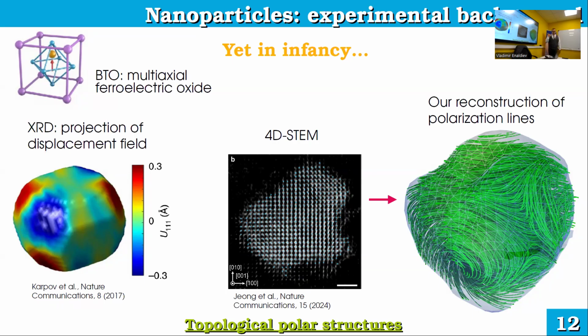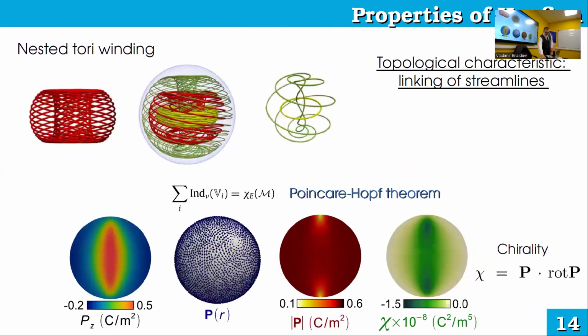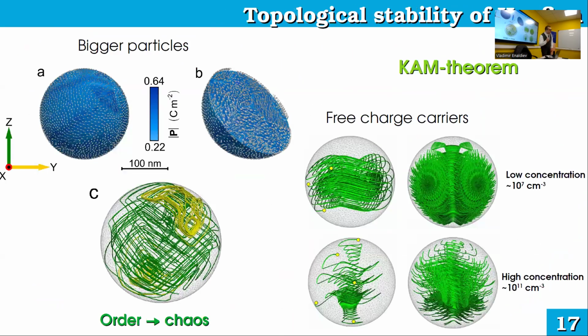Because it's also very important that I showed it has topological stability. You can get smaller or bigger nanoparticles. You can introduce free charges. You can introduce bound charges. You can introduce electrical fields. You can introduce some elastic deformations. And with some values, this state resists, but somehow gets deformed. With some big values of these perturbations, of course, this hopfion state is destroyed.